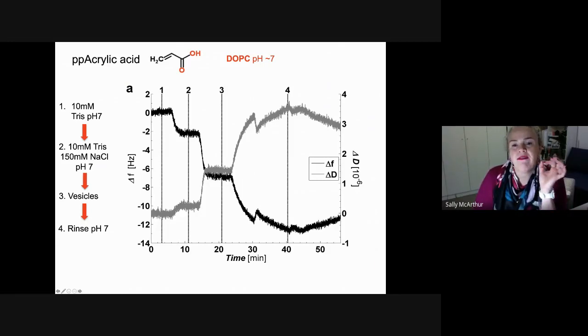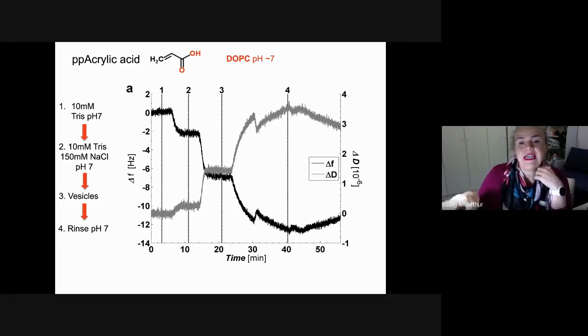But the minute you have a vesicle on the surface, obviously it's viscoelastic. It's a water bag, basically. So its viscoelastic properties are really soft. So the dissipation component rises. But you rinse in pH 7 and you can see you're holding some of those lipids on the surface. But the amount of material that goes on at pH 7 is really small.